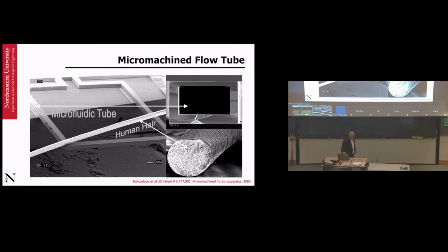Anyway, we did this, and the first thing that happens, if you don't do anything, is that just by flowing a fluid, the tube becomes heavier, and the resonance frequency changes by the mass. So the resonance frequency is a function of the density of the material, and the twist is a function of the flow rate. What is nice about this is that this is an absolute mass flow sensor. With compressible fluids like air and any gas, it's much harder to measure flow. Water is easy to measure because we know the density of water and it's not compressible. But with air, it depends upon how it is getting compressed. So now you can measure compressible fluids in absolute mass, as given by the previous equation.